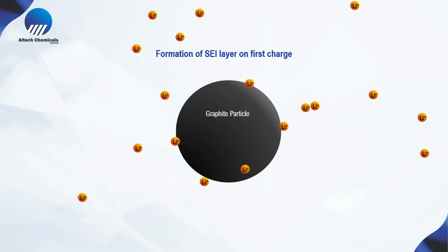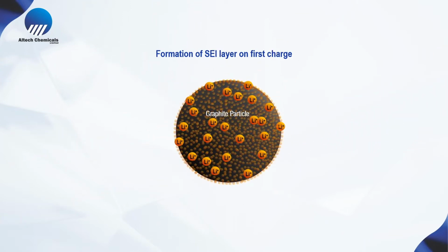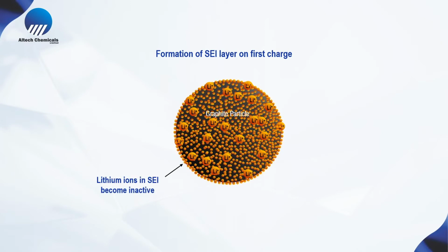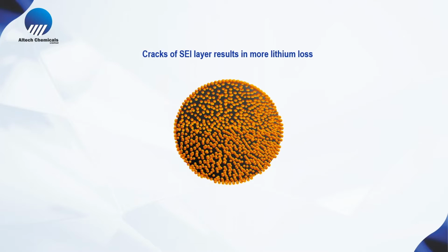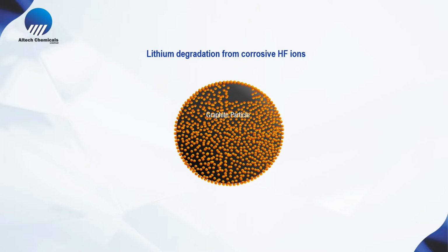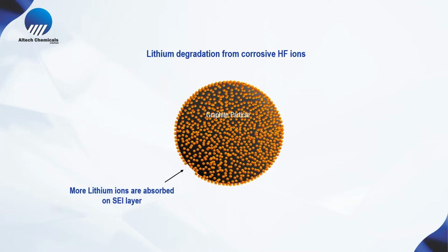Essentially, what happens in a battery is the lithium coats the graphite particles and forms an SEI layer around the graphite material, and all that lithium becomes inactive. So this is a big problem for the battery industry, because 10% of your lithium doesn't take part in the future of the battery. Also, during the performance of the battery, there are cracks that happen in the SEI layer, and then more lithium is absorbed. And also during the performance of the battery, hydrofluoric ions in the electrolyte break down the SEI layer, and then more lithium is absorbed onto the particle as well. So there's a continued degradation of lithium on that graphite particle.